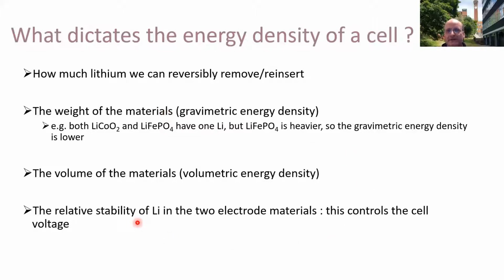And then the final thing that dictates the energy of the cell is essentially the relative stability of the lithium in the two electrodes. We're shuttling lithium from one electrode to the other. When we charge the battery, we're essentially driving it uphill, to an unfavorable situation. And then when we're using the battery, it's going back downhill to a more favorable situation. That difference in energy between the lithium in those two electrodes will dictate the cell voltage and consequently the overall energy of your battery.